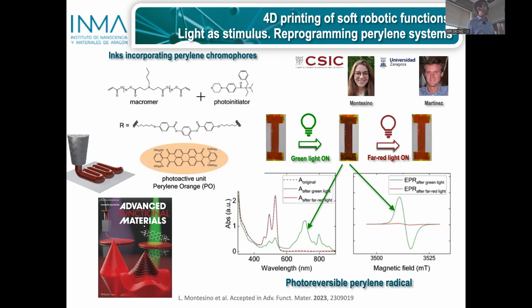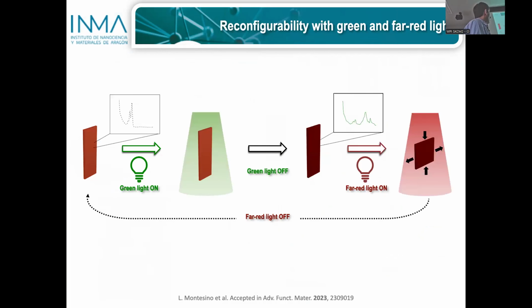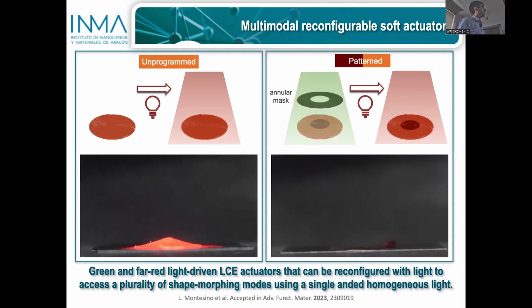So with this, we have the original system, that is not sensitive, or very little sensitive, to far red light. And the system programmed with green light absorbs a lot of far red light. So we can excite the system with far red light and get a strong deformation. With this, we have used it to program these materials. In the unprogrammed version, here you have the spiral, and when you irradiate with far red light with sufficient intensity, the absorption is low but sufficient to generate the cone.